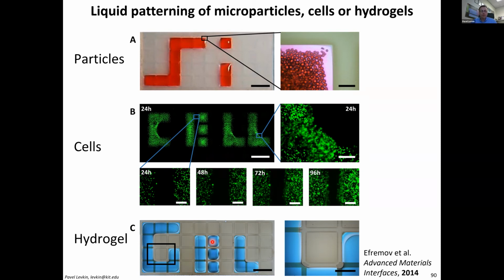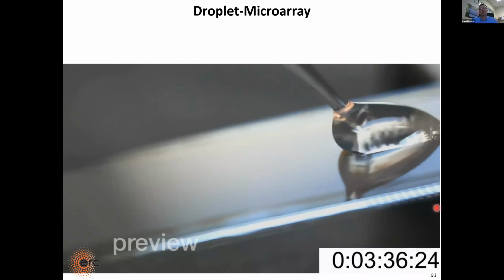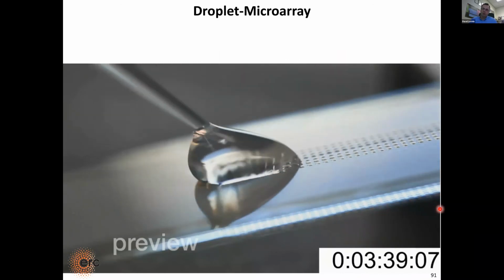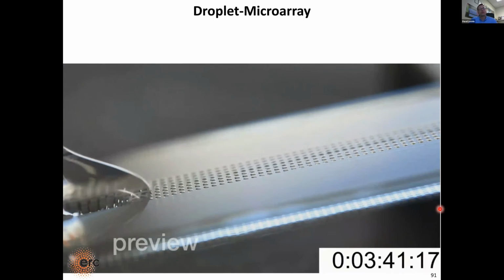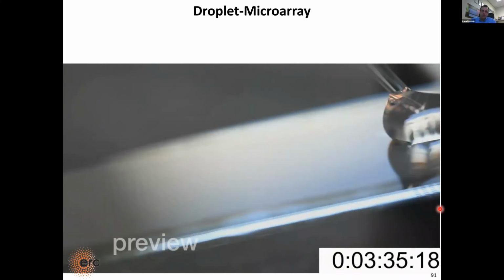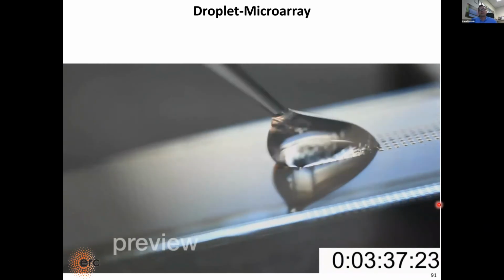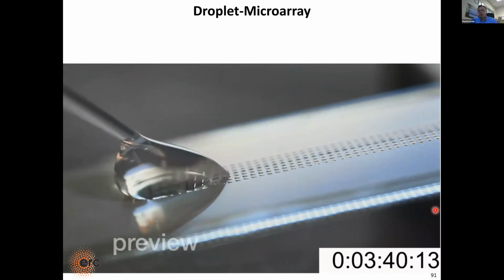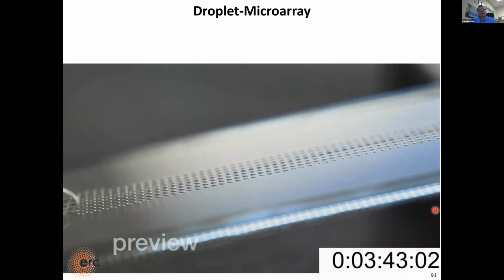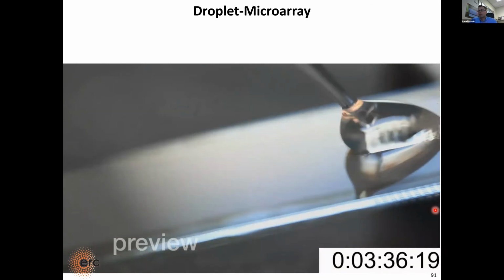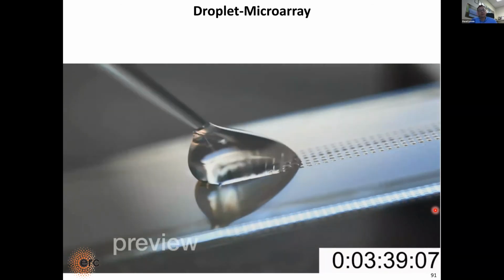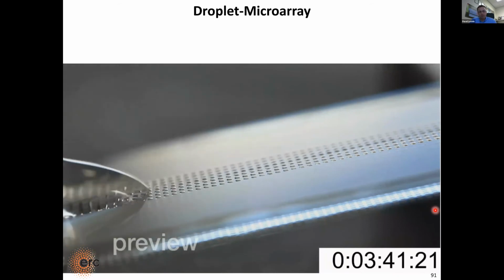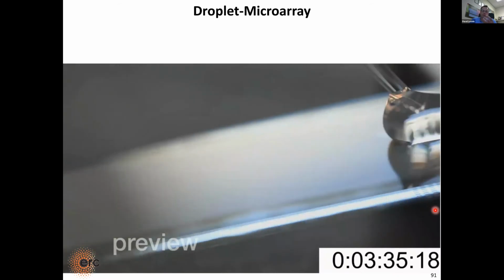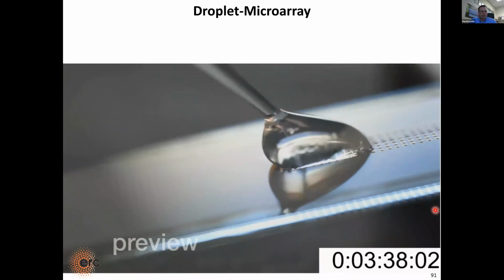And then when we use this method to make a microarray of superhydrophilic spots on a superhydrophobic background, we found that if you just roll a droplet of water on the surface, you can in one step form thousands of nanoliter sized compartments in every single hydrophilic spot, without multiple pipetting. So it's even single step multiplexing of one solution between thousands of compartments.